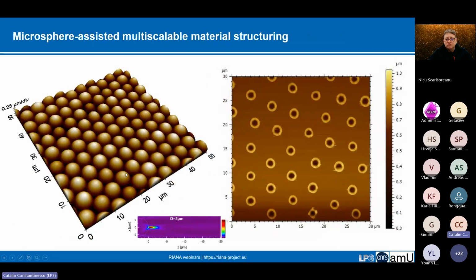Just to show you an example, we used here a monolayer of spheres, which are 5 micrometers in diameter, and the nanojet that ablated in a tantalum thin film deposited on a silicon substrate created this structuring matrix. So the whole idea of this structuring, this printing, these subtractive applications, is just to illustrate the maturity of our approach here at LP3, and to further show that all these techniques are available in the RIANA consortium framework.